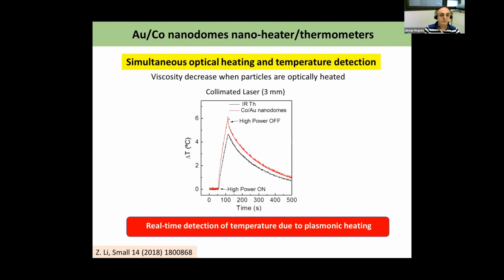Actually, there is a slight difference in temperature between the infrared and the nanodomes and the phase lag. This is because the infrared only measures the surface temperature, and it takes some time for the temperature to diffuse through the whole liquid, while the nanodomes measure the temperature inside the liquid surrounding the nanoparticles.